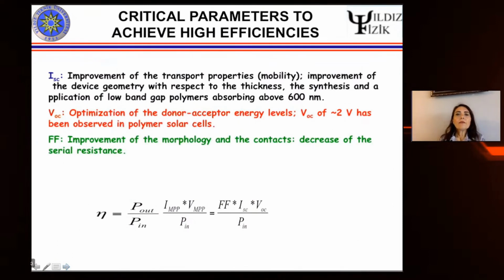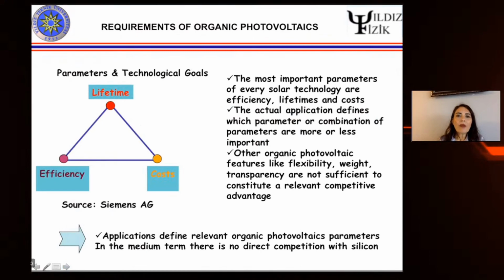What are the critical parameters to achieve high efficiency? The efficiency is directly proportional to these parameters, and we know how to improve this. So as a result, short circuit current density, open circuit voltage, and the fill factor are the important parameters to improve the device performance. And as you can see, improvement of the transport properties, mobility for example, photon harvesting by using low band gap polymers absorbing above 600 nanometers, or the optimization of the donor-acceptor energy levels can improve the device performance.